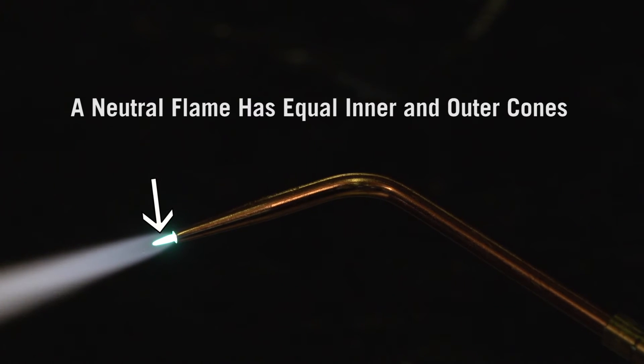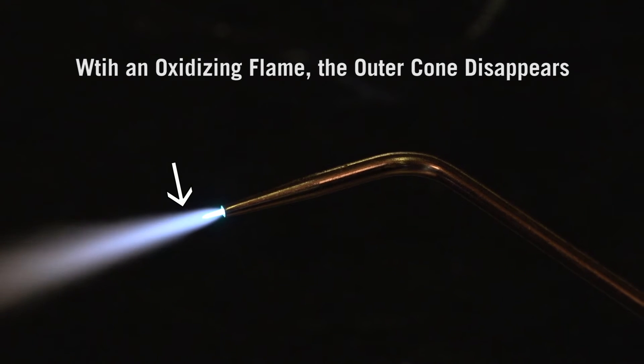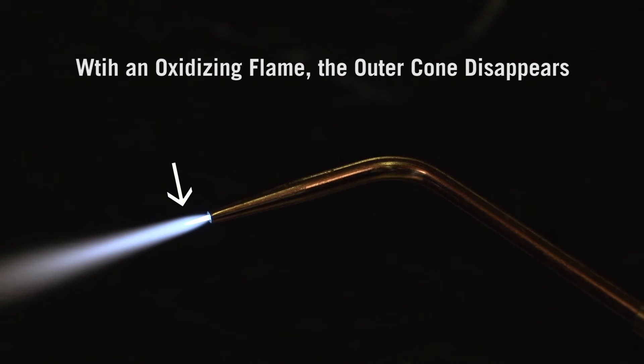You will hear a slight hissing sound. If you add too much oxygen, the outer cone disappears. The inner cone becomes pencil sharp and a loud hissing sound occurs.